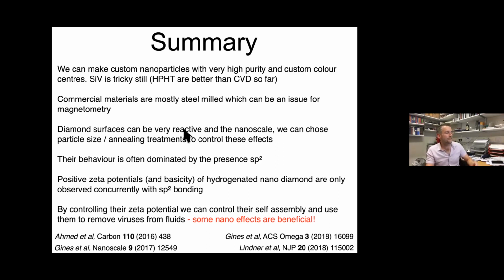These diamond surfaces are super reactive. The smaller they get, the more weird they get, right? So be really careful about that, because it's this sp2 thing, you can't ignore it. And like I say, with the positive zeta potential, you only see that with hydrogenated material at the same time as the sp2, and it comes with the basicity at the same time. So for me, this is a red flag. It's sp2 related.